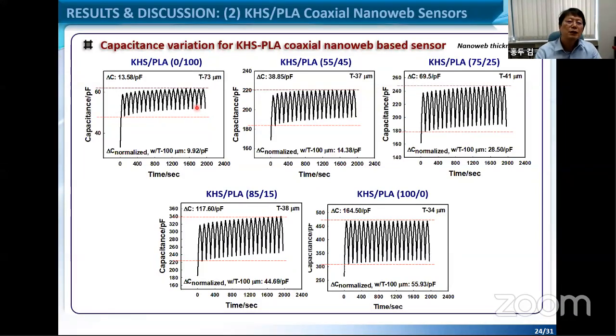So if you increase some KHS, the capacitance change increases, as you see. At 100% KHS, of course, it is the best in terms of the capacitance variation. But for our purpose, maybe we can try to use something in between, something like 50% of the KHS and 50% of PLA, depending on the applications.